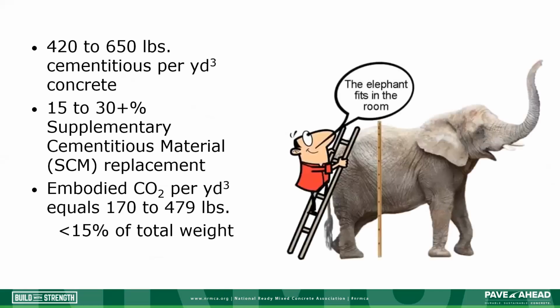We also need to remember that a 1-to-1 ratio of CO2 refers to Portland cement, not Portland cement concrete. So 1 cubic yard of concrete typically has 420 to 650 pounds of cementitious materials. If we factor a 15 to 30% replacement of Portland cement with supplementary cementitious materials like fly ash and slag, we can calculate the embodied CO2 for 1 cubic yard of concrete is between 170 to 480 pounds. That alone is less than 15% of the total weight. So if we look at the whole picture and apply life cycle thinking, we see that the elephant does indeed easily fit in the room.